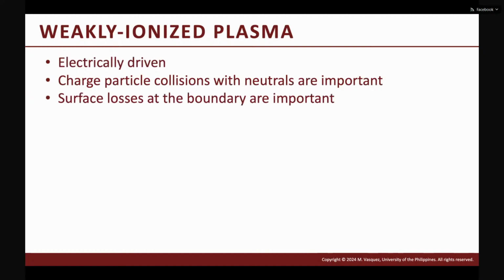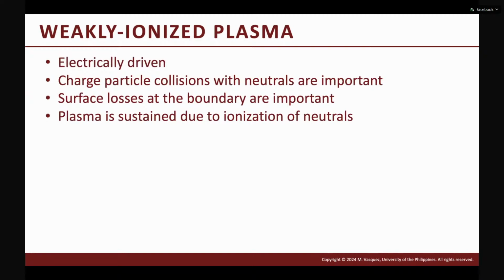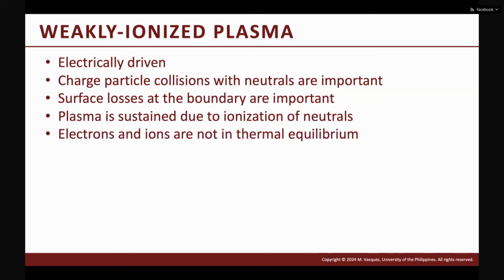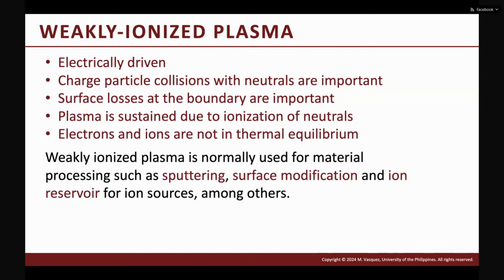So in our work, we actually use weakly ionized plasma, low temperature plasmas. And for us to produce this plasma, it should be electrically driven, so either using DC or RF. And then because it is weakly ionized, you have more charged particle collisions with neutrals. And this is where different effects are induced through these collisions. Surface losses are also important at the boundaries, and plasma is sustained due to ionization of your neutrals. And as I mentioned earlier, electrons and ions are not in thermal equilibrium. So it is this type of plasma that we use for different material processes such as sputtering and deposition, surface modification, and can be used as ion reservoir for ion sources.